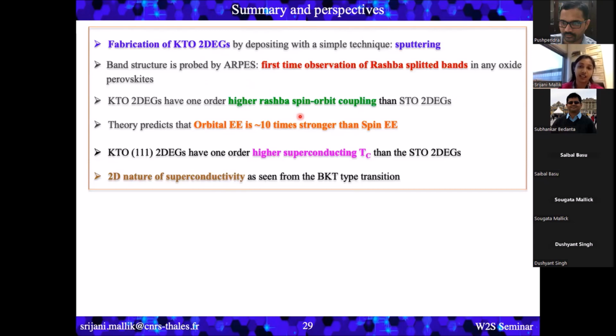Also, theoretically, we predict that if we can use the orbital Edelstein effect, it's like 10 times stronger than the spin Edelstein effect. Also, with KTO (111) 2DEG, we could get a very high superconducting TC compared to STO 2DEGs. And we could also prove the 2D nature of superconductivity from the BKT-type transition. But as I said, a lot more to do in future.